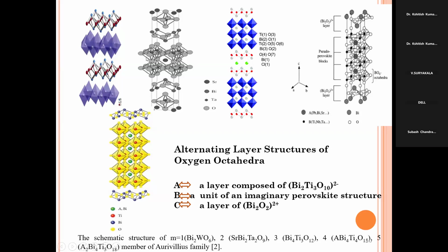In the second figure, this is the bismuth oxide layer, and this is the perovskite layer. So the second one is the two layer structure, this one is the 3 layer structure, this one is the 4 layer structure, and this one is the 5 layer structure. If the number of layers is more, the material has the fatigue-free property, and the property is good for the material. So this is the 5 layer structure.